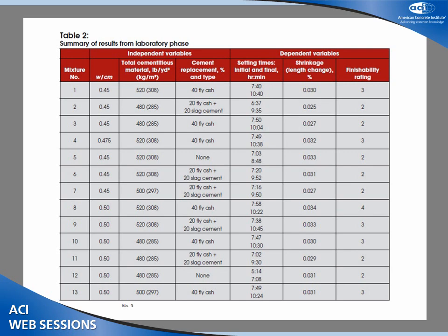Again, I can't argue with it. The straight Portland cement here with no replacement was the shortest set time. I should point out, I guess briefly too, fantastic shrinkage values of all of these mixes. And then this last one is the finishability rating. 1 being the poorest, 3 being classified as moderate, 4 good, and then 5 is excellent. We didn't have any 5s. But we certainly had several. I mean, if you take a look at these, even the straight Portland didn't get a great rating. So many of these had better ratings than the straight Portland.